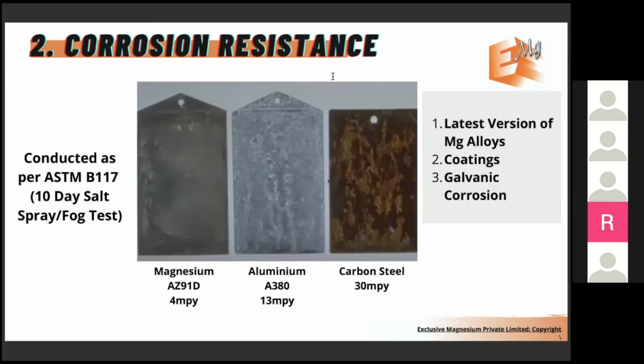The reason I'm mentioning it is because a lot of the understanding of magnesium comes from older data about magnesium, the capability of magnesium alloys. Whereas with the revision of the series of the alloys, the more purity we were able to create. Say, iron, nickel, there are components in alloys which create that corrosion effect in magnesium. And when you remove those out of magnesium, they no longer are corrosive.